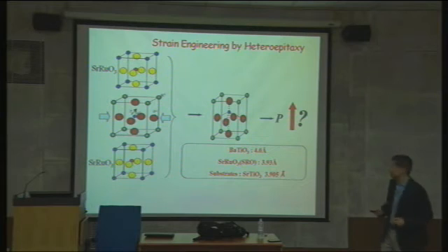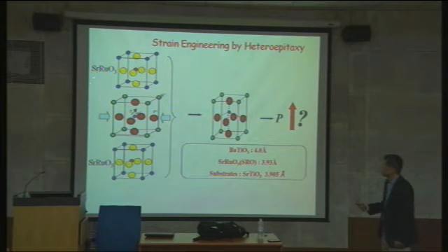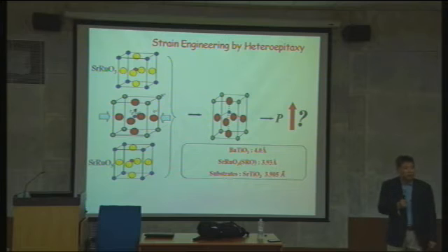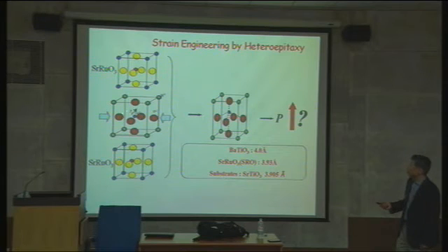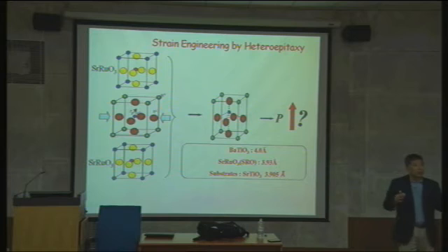Okay, great. All right. So the heteroepitaxy of barium titanate is one of the great examples of strain engineering in perovskites. I briefly introduced ferroelectricity, and ferroelectricity comes from the off-center titanium in the tetragonal barium titanate system. When you apply strain and elongate it, the displacement of the titanium atom can be much further. That enhances the remnant polarization, and at the same time, the energy barrier to coming back to the paraelectric state is much higher, so it is stable up to very high temperature. That's the basic hypothesis of this strain engineering.